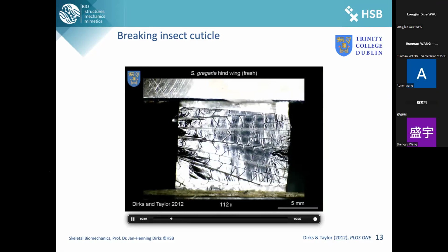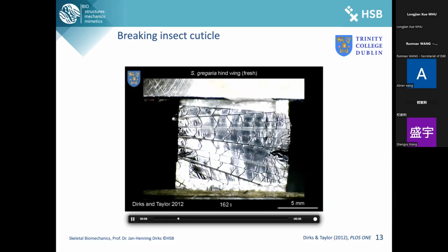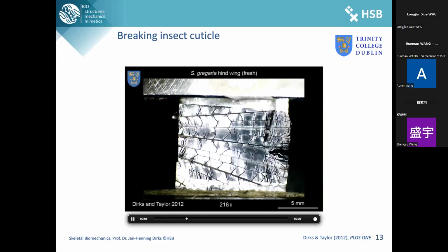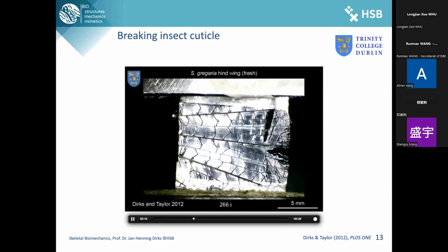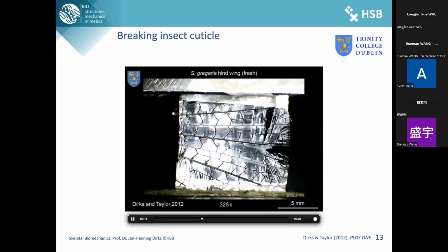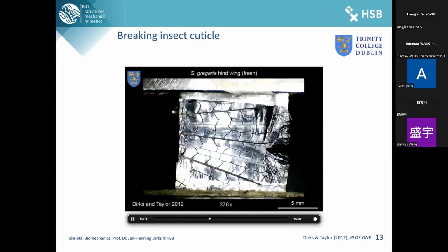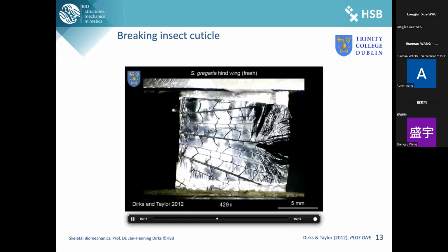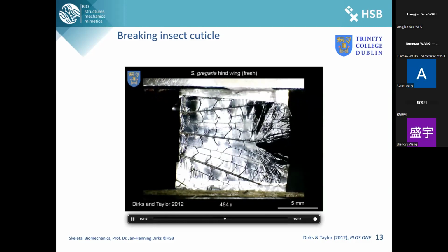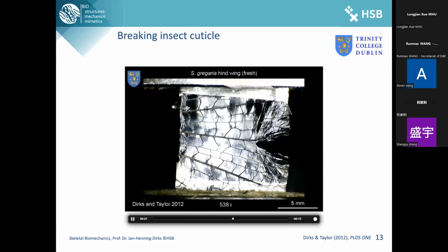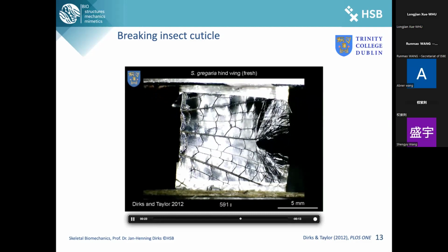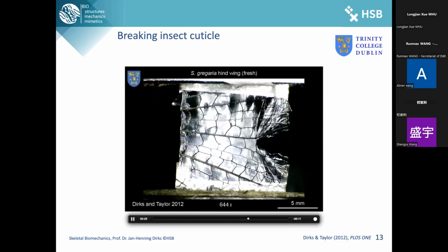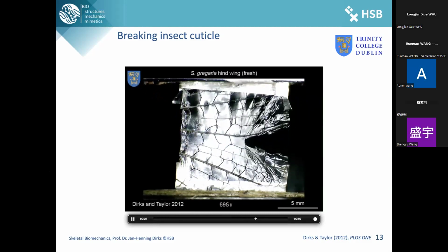And as you can see, at some point the crack here, the notch, will start to grow, and then basically it will hit a cross vein, as we call these veins. And the engineers in the audience will see that something interesting happens. It's delayed, so it's stopped by this cross vein. And then at some point, the cross vein breaks. The machine is luckily strong enough, it was very expensive, to break an insect wing. So it runs through the entire wing, and then it propagates even further after breaking the next cross vein, and so on and so on.